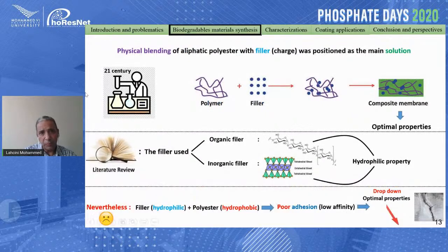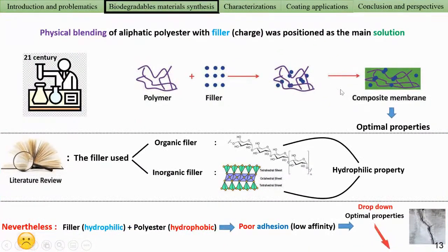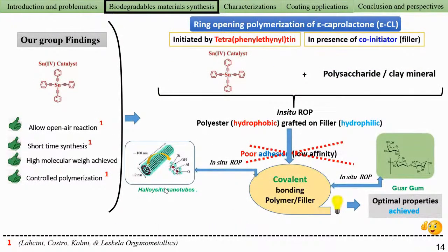But in our case, our polymer is an aliphatic polyester, and our fillers are either polysaccharide or halloysite nanotubes or clay. Both are hydrophilic. Normally, we melt and mix, and we should have a composite with good properties. But in our case it was really difficult to get this, as our polymer is hydrophobic and the fillers are hydrophilic. It was really difficult to have a good dispersion, a good adhesion between both. Then we opted for in situ ring-opening polymerization of epsilon-caprolactone or lactide with filler.